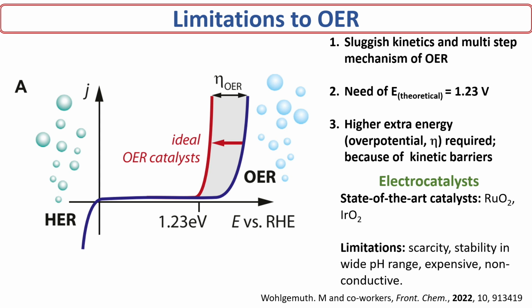Whenever you use electrocatalysis, even then you have to apply a certain additional potential to make this reaction happen. This is called overpotential. So you have to apply a potential over and above the thermodynamic potential, which you call the overpotential. And you can see that the higher the overpotential, the less effective the catalyst may be.